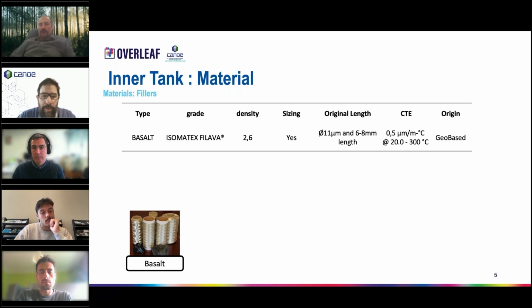These materials have a pretty high density, like glass, close to 2.6. And as you can see, the thermal expansion is much lower than the polymer's, because the polymer, if you remember, is close to 25, and here it's below 1. So that's why we made a lot of trials and measurements, which you will see later on in a slide, just to control this behavior.